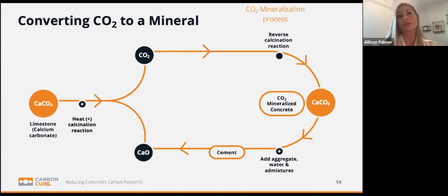These reactions increase the overall strength of the mix and is a key element to the success of the CarbonCure technology. The CO2 will make your concrete stronger while allowing you to reduce your cement content by about 5 to 6%. Without impacting fresh or hardened properties.